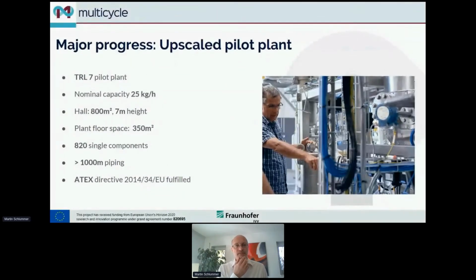However, in the end, we managed to provide an upscaled pilot plant at TRL 7 with a nominal capacity which looks rather low. But if you see how large the plant is, it demonstrates that each of these containers we were using is just a bit smaller than in industrial commercial scale, but all the rest, all the surrounding supply, needs to be more or less at the same scale as for a commercial one. We have a hall with 800 square meters, 7 meters height, a plant floor space of 350 square meters, 820 single components, and more than 1 kilometer of piping.